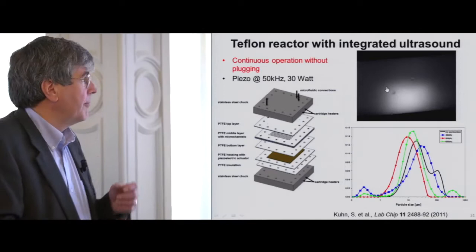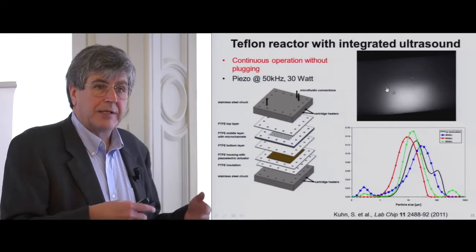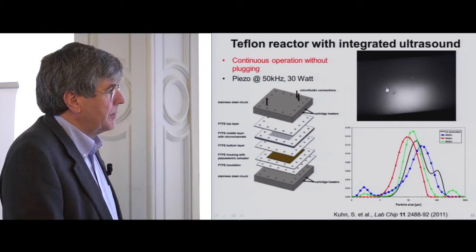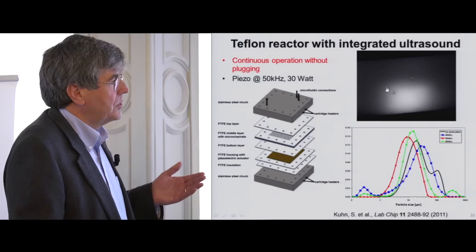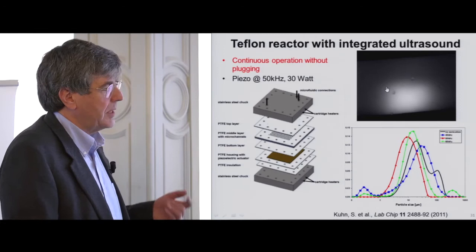This is a simple micro-reactor built with that principle. It has a Teflon channel structure — it's very difficult to nucleate on Teflon, so we don't get so much deposition. This is sandwiched with a piezoelectric element to control the input frequency. Without any ultrasound input, you see large crystals that would begin to bridge a 400-micron channel. As we add in the ultrasound, we can bring crystal size down to about 10 microns, which can then flow through the system.